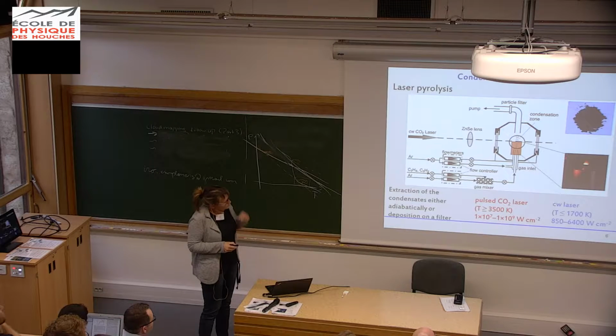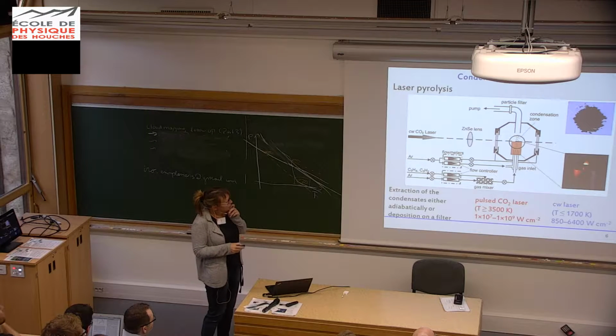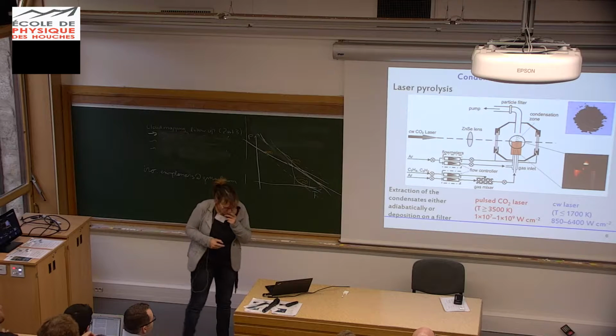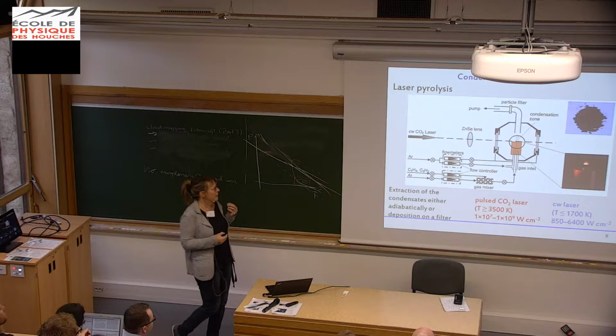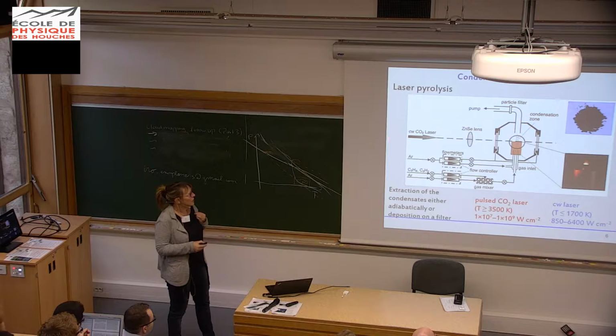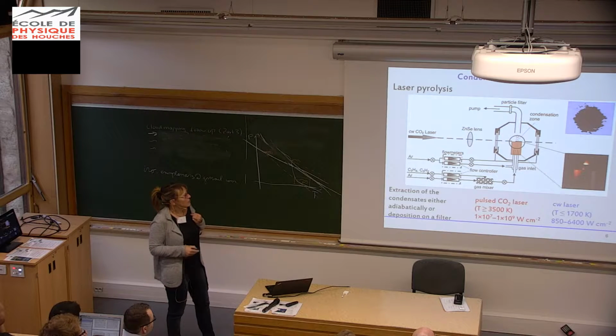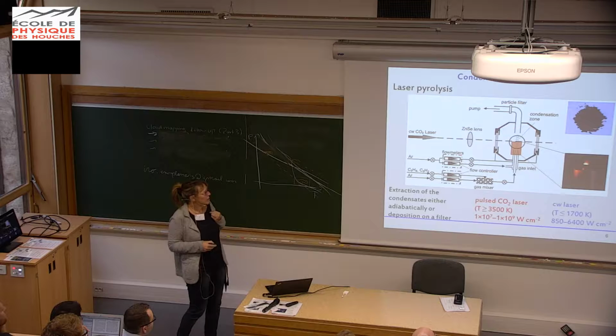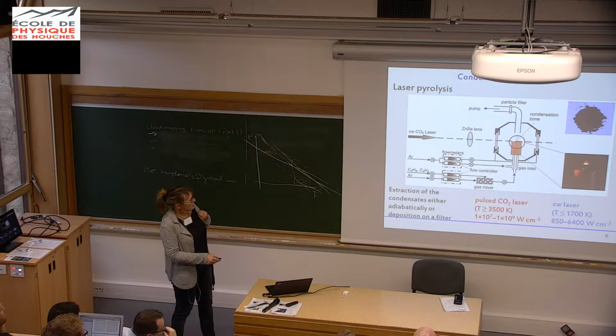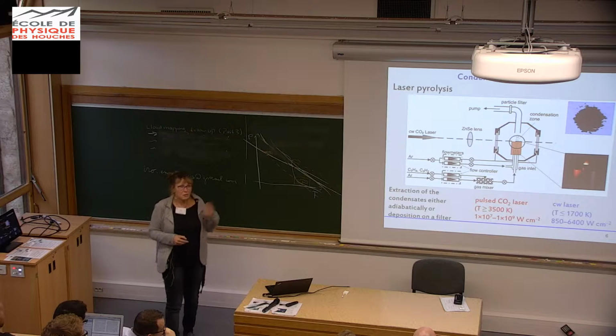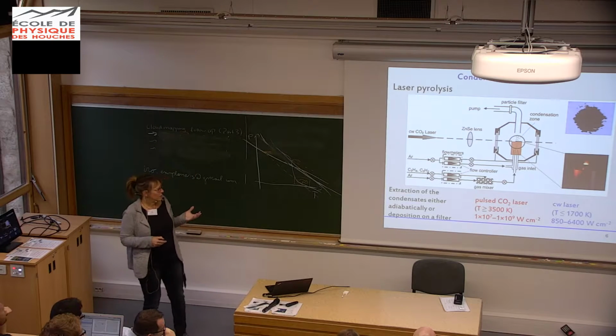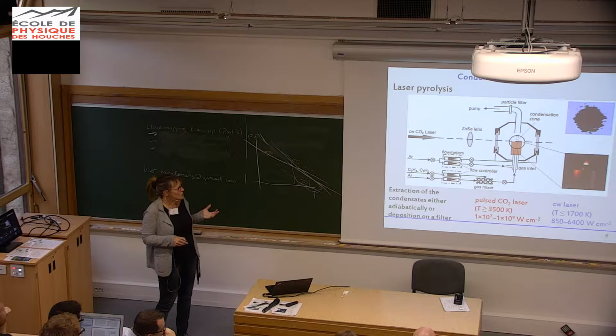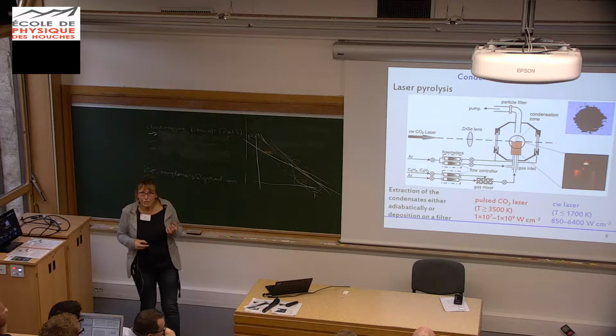The temperature in the condensation zone is one important thing we can influence by choosing two different types of lasers. If we use a pulsed one, we have a very high power density in the dissociation-condensation zone, between 10 to 7 and 10 to 9 watts per square centimeter, and you can correlate this to a temperature - this means we achieve temperatures larger than 3500 K.